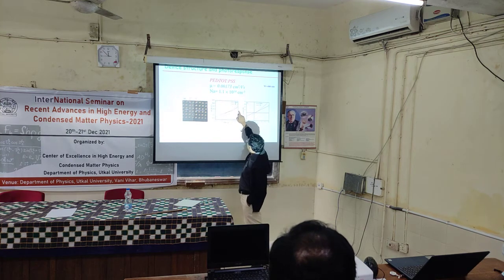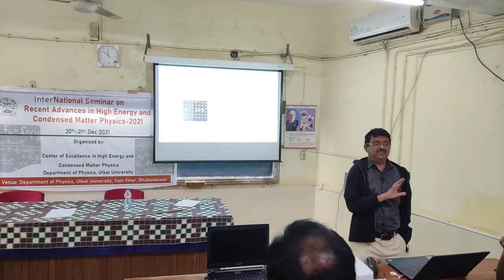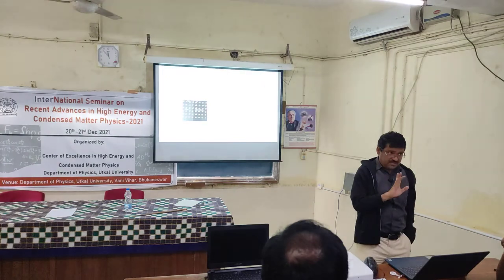But look at the IV characteristic, it is non-linear. At minus 200 it is around 500 nanoampere, whereas at the other side it is around 600. There is a slight asymmetry. So it is basically not a perfect PN junction. However, when we shine light, as you see here, this is the dark current, and when we shine the light, there is a current.